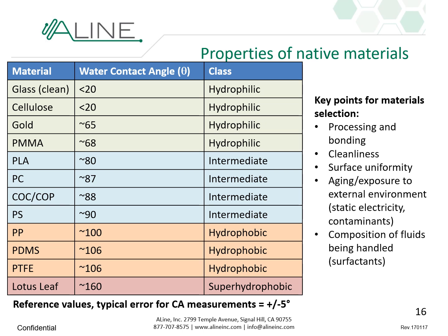and change its properties. You also want to think about the surface uniformity, depending on how you're processing it. It might have some imperfections, some roughness, the things that may actually induce a higher hysteresis. Even if the contact angle is in the range you want it to be, it might actually make it a little bit harder for you to achieve the goals that you're looking for.